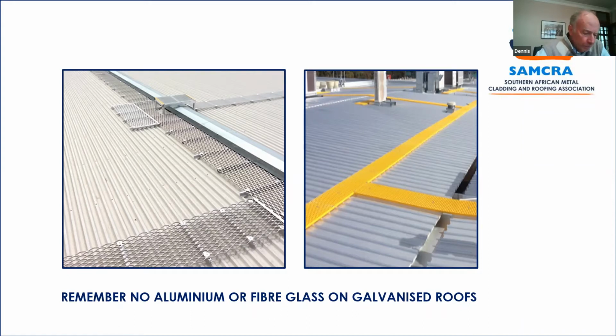The problem is, expanded metal, you cannot hot dip galvanize. So you're stuck with it either painted, or in the case of the Mentex product, they punch it out of pre-galvanized material, 1.6 pre-galvanized material. Now there's a correlation between the size of the apertures and the thickness of the coating as to how long you will get cathodic protection on the cut edges of that diamond mesh or expanded mesh, whichever you want to call it, before you get an onset of rust.